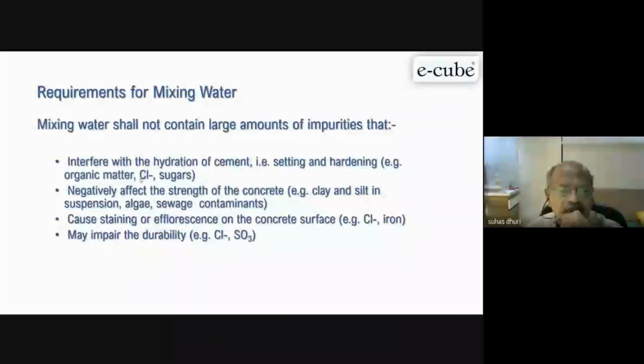Now, any salt coming causes staining on concrete, or you get efflorescence. You must have seen some concrete outside walls with white patches. Water comes by capillary action, the water evaporates and salt remains on the surface. That is your chlorides or iron. You can see brownish stains in concrete. In most old structures where corrosion has taken place, the ferric oxide is dissolved and comes to the surface. So it is affecting your durability. That we have to understand very carefully.